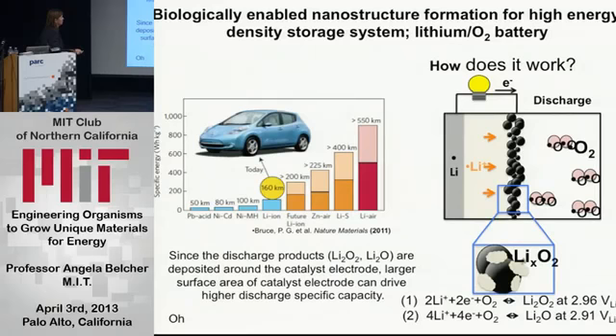And so we looked at this and said, is there anything that we can do? Is there anything a virus can do to help solve this problem? And one of the problems is during discharge, the discharge product, which is lithium peroxide, is deposited on the electrode itself, and it's part of what reduces the reversibility, and so you need to be able to have it reverse back. And the other part is as this discharge product builds up, it actually clogs the pores and reduces the catalytic efficiency of this.